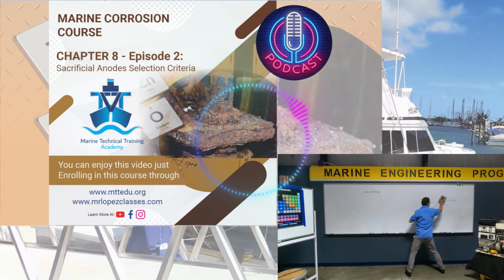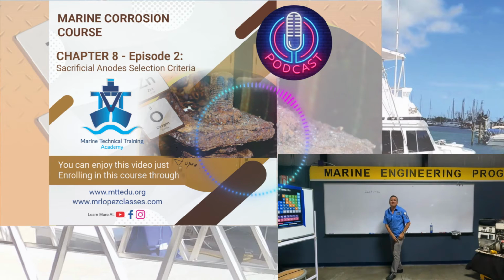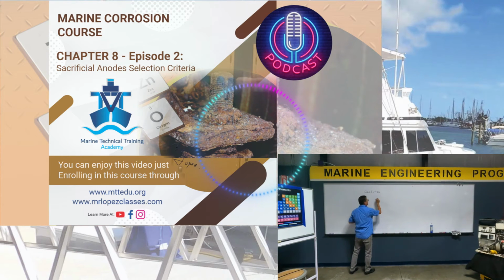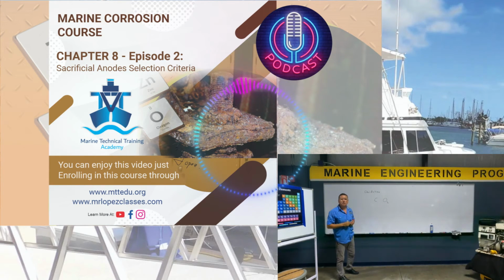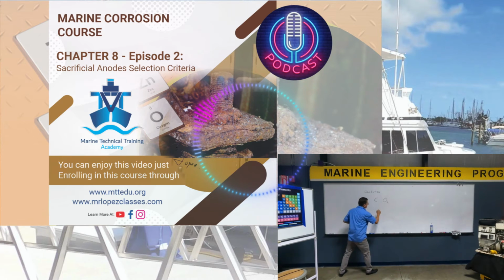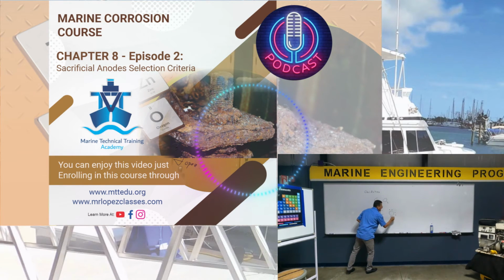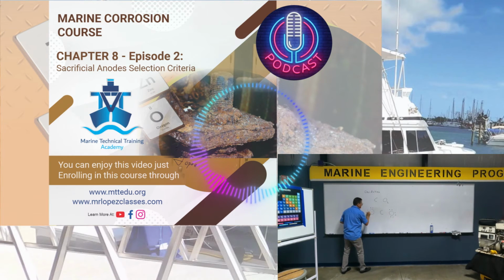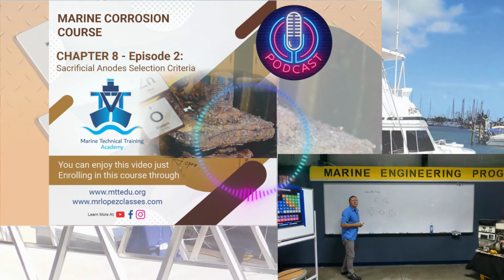For that reason, you need to be careful with those magnesium alloys because in some cases they produce overprotection. In some waters and some hull materials they produce overprotection. For that reason, it's not recommended in some situations. In terms of electronegativity, it's the best. It's the less noble alloy in order to protect other metals. But in some cases it produces overprotection. What happens if you have overprotection? You produce a lot of magnesium oxide covering the surface of the other metal, and probably this is not good.